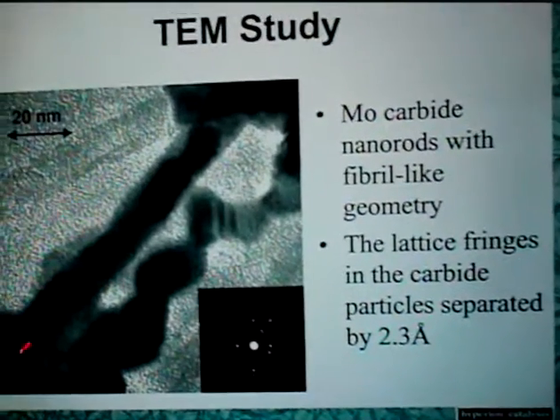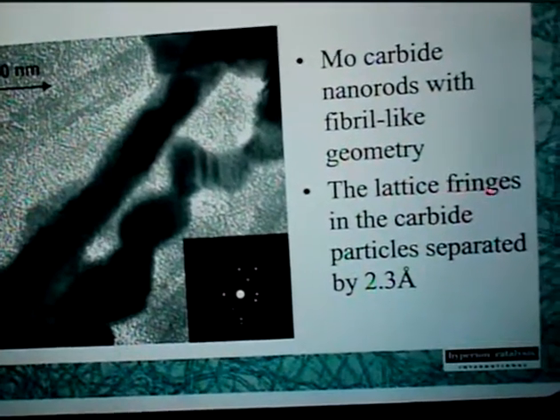I guess that the people that are experts on this area, the people that do really the TEM, if you really want a confirmation that this is what you're making, you keep the structure. Here you zero in into one of the fibrils, and here are some defects that I mentioned to you that those carbon nanotubes have. They are not a nice straight tube. They have many defects, and so people can recognize their material very readily because of those defects. But in fact, this looks like the molybdenum, the fibril. But if you look at the lattice fringes of this material, it corresponds to the one that's actually for the carbide. So we know for many methods, many ways, XPS and XRD and now TEM, that this is actually molybdenum carbide that is formed.